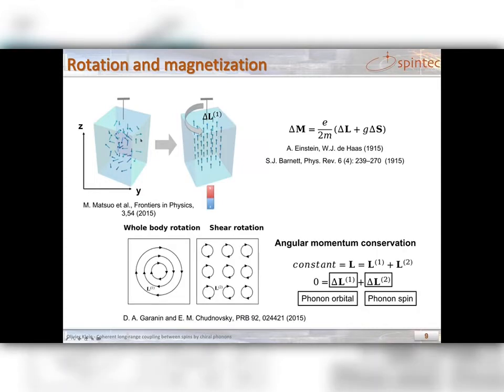But because of angular momentum conservation, when you do this kind of whole body rotation, there should be also a localized shear wave rotation associated. So it can be considered that this whole body rotation corresponds actually to phonon orbital angular momentum, while the localized shear wave rotation corresponds to phonon spin angular momentum. And what we are going to discuss in this talk is all about phonon spin angular momentum.